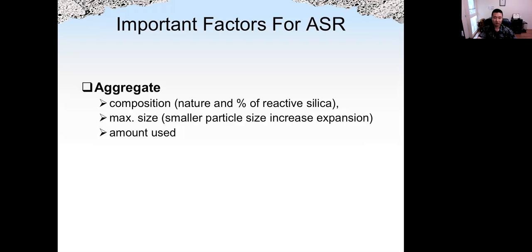So for the factors affecting ASR, from the part of aggregate, composition is very important. So the nature and percentage of reactive silica. Okay, some aggregate does not have silica at all, so we don't need to care about ASR. Even if the aggregate has silica, if it's not reactive, we still do not need to worry about ASR. So if the aggregate has reactive silica, then the size of aggregate will be a factor. Smaller particle size will increase expansion, because the smaller the particle size, the interface between the aggregate and the cement will be higher. So we have higher potential for the reaction between alkali from the paste and the silica from the aggregate. Okay. And the amount used is also important. The more aggregate, the more potential ASR.